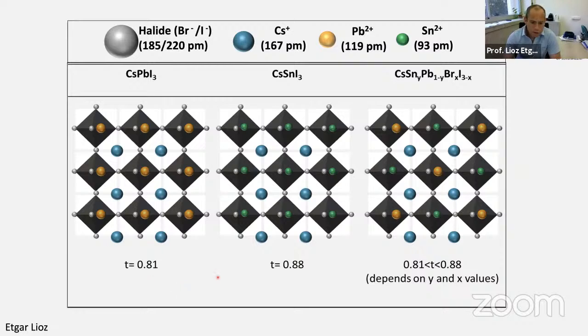If we look at the tolerance factor here on the bottom, the tolerance factor tells us if this perovskite can really form. And indeed, if it's over 0.8, it can form, but this also tells us that this tolerance factor is not the accurate parameter to look at. Actually, it was invented for oxide perovskite, and this is why it's not so accurate in this case.